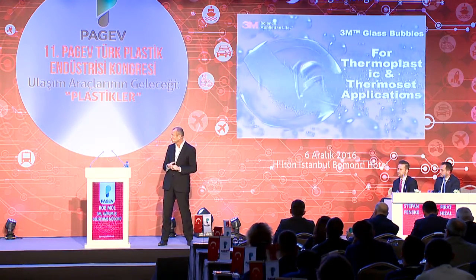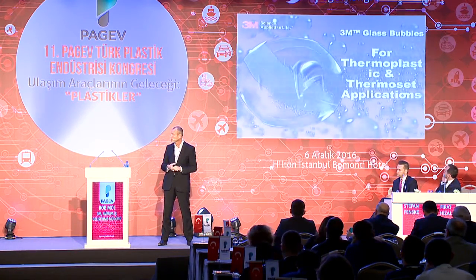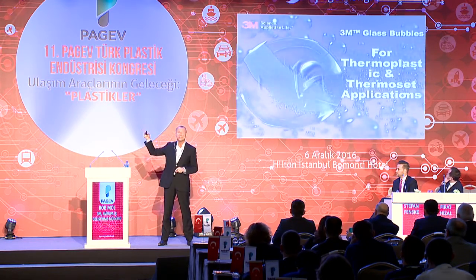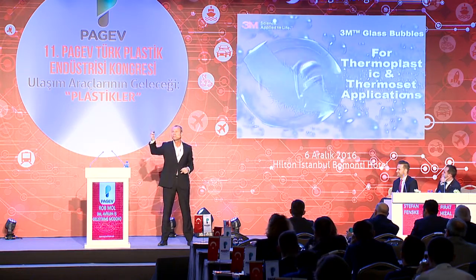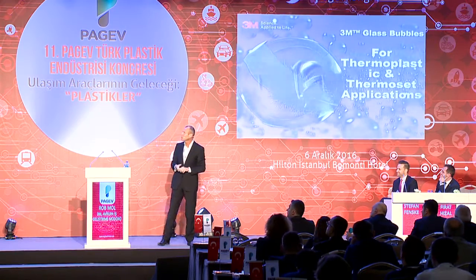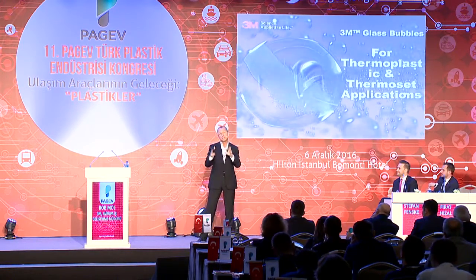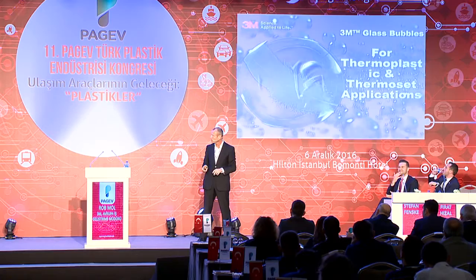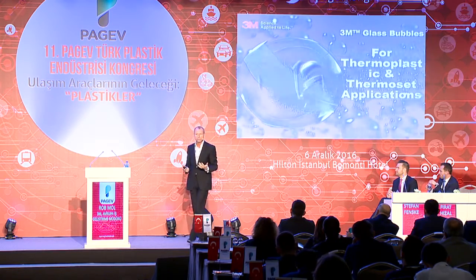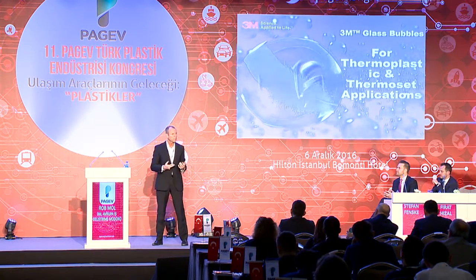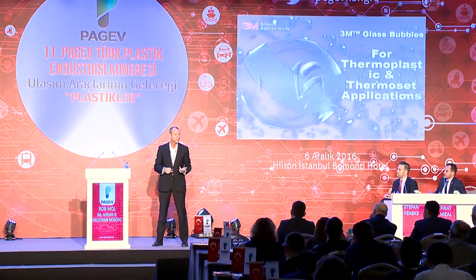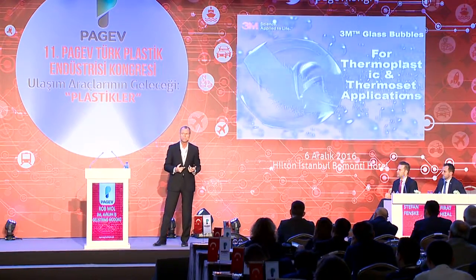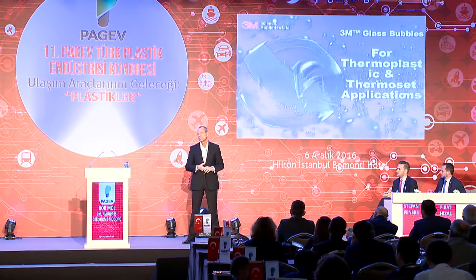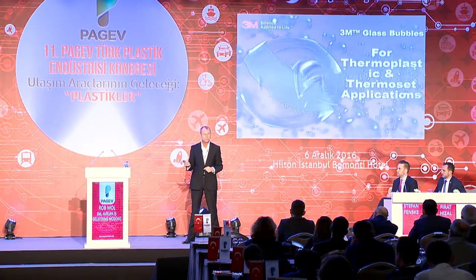And it's funny, if you look at the picture, this morning I was looking around, and it seems like there are glass bubbles all over the place here, because they look the same as the lights here. But actually they look like that if you put them under a microscope. It's one of the 3 ways to make plastic parts lighter. You can do that with thin walling, you can do it with foaming, which was mentioned already in the previous presentation, and you can do it with the use of glass bubbles, so using a lightweight filler, because that's what it is.